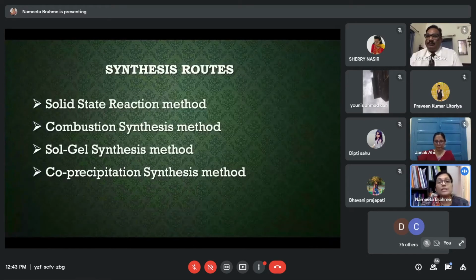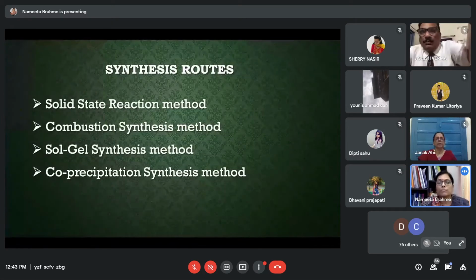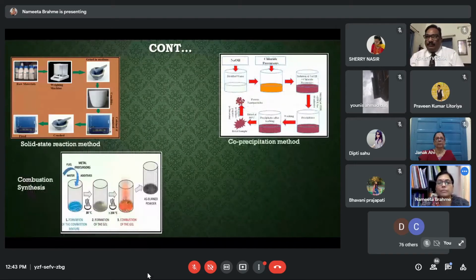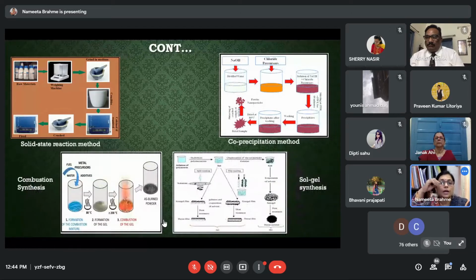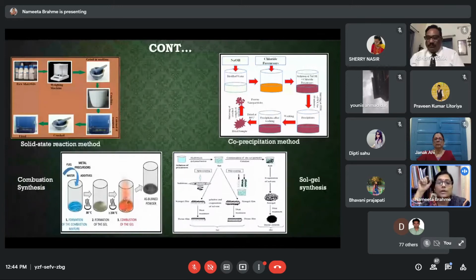Now, about the synthesis route. Now because we have decided on phosphate, there are very many methods. I will summarize them very quickly. Solid state reaction method is the simplest and the most ancient method, also with high probability of forming pure compounds. In solid state reaction method, the raw materials used are generally metal oxides and carbonates. Initially, all the raw materials are calculated and weighed following the stoichiometric rule of chemistry.